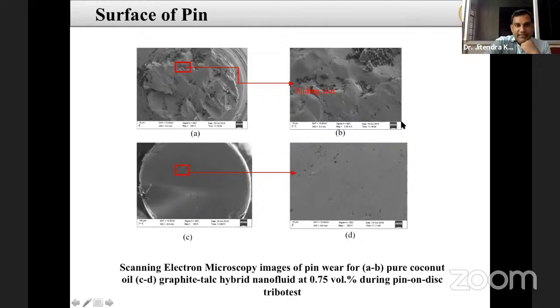After this analysis, we checked the sliding pin, to see what happened on that particular pin and why it shows those results. This is with pure coconut oil. You can see the cluster and sliding scar, and some cluster formation has happened. So the surface is very uneven, and that's why the coefficient of friction is higher and wear is also more. But in the case of graphite and talc with 0.75 volume percentage during the pin on disk test, you can see a very smooth pin surface. Because of that, we also observe very low friction in the case of the 0.75% concentration of the fluid.